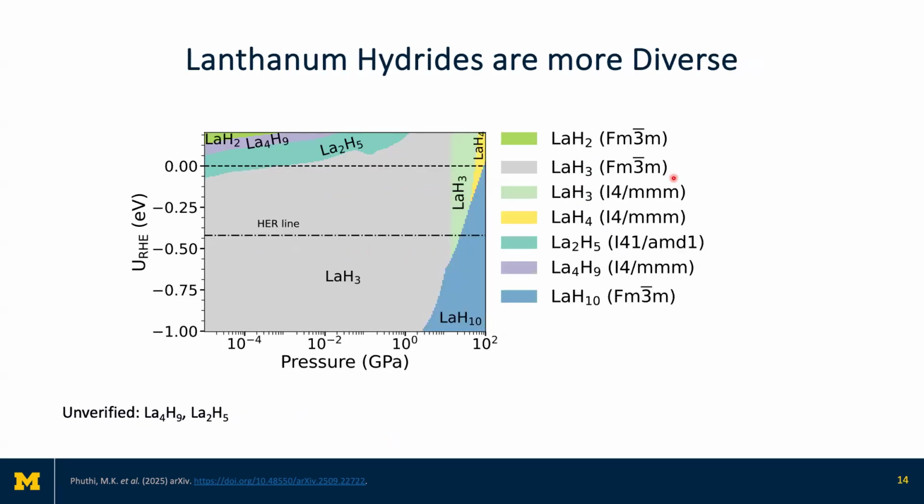And then there's lanthanum. Lanthanum, of course, is a really important and well-studied material, particularly in the superconducting space. This has quite a rich phase diagram. LaH10 is a very high temperature superconductor, the same as YH9 actually, right? So this was synthesized in pressure cells on the order of hundreds of gigapascal. I forget the number, it might have been close to 200.